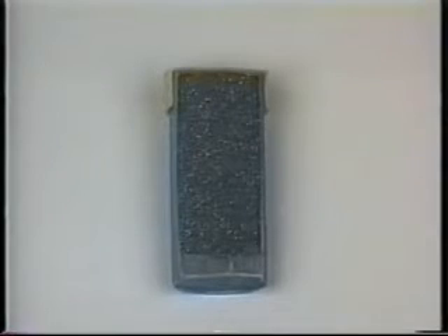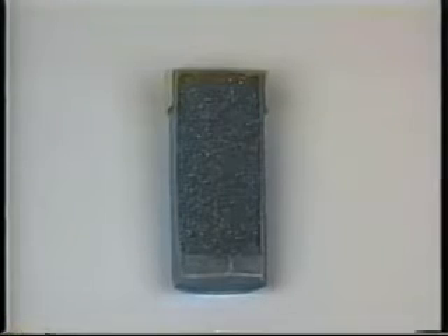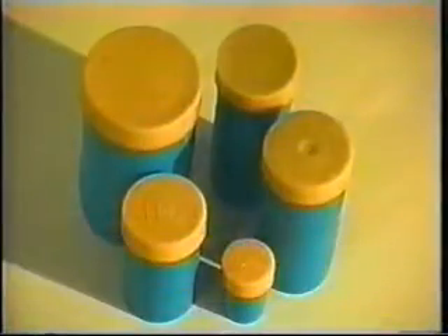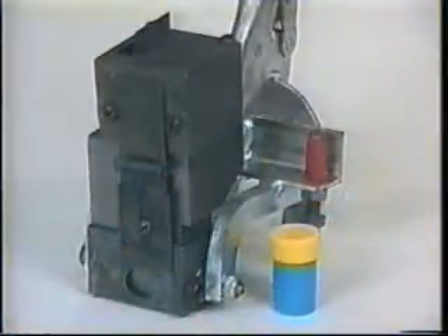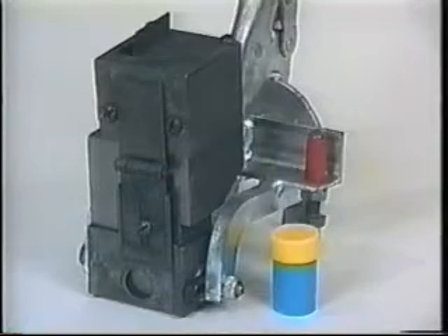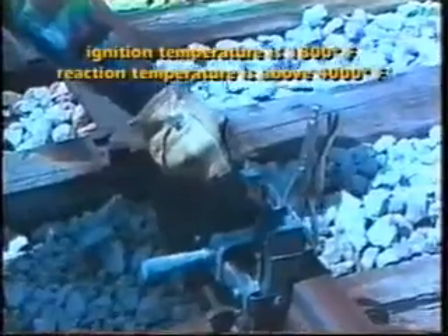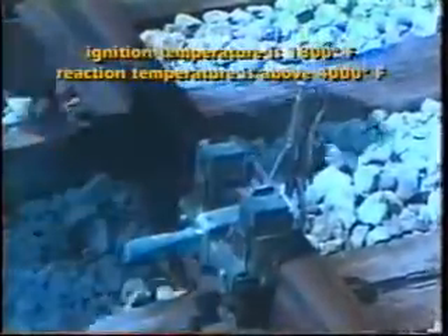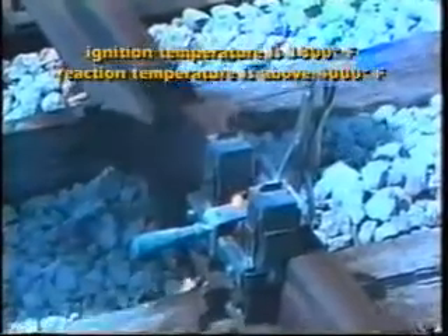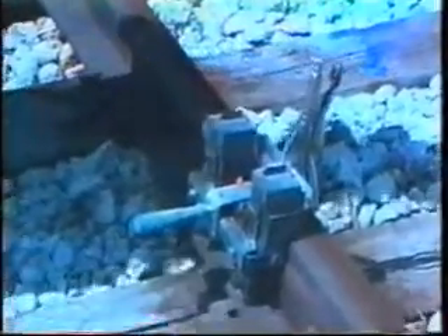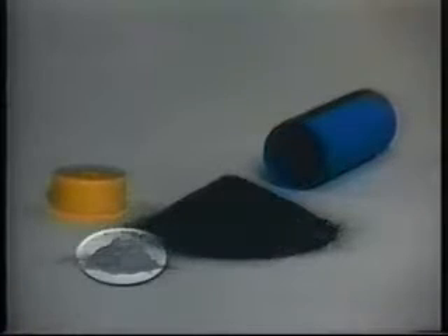The tube containing the weld metal is divided into two parts: copper oxide granules and the starting material. Copper oxide granules, which make up the exothermic welding material, are the bulk of the material in the tube. The tubes are sized in gram units, and the mold and weld metal relationship is pre-engineered to produce a desired result for each specific application. The ignition temperature of the weld metal is 1800 degrees Fahrenheit, and the reaction temperature is in excess of 4000 degrees Fahrenheit. The starting material contains the same elements as the weld metal, only in a finer particle size.